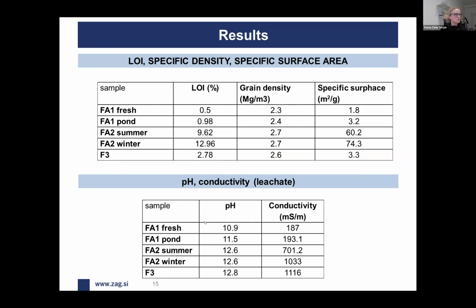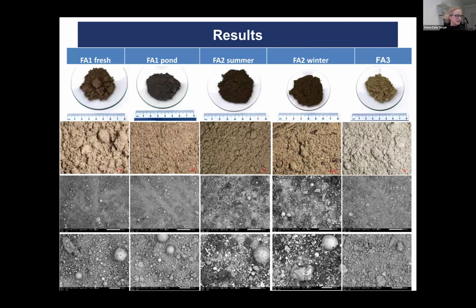Then we specified also some other physical properties, such as loss on ignition, grain density, and specific surface. What is most obvious in the loss on ignition is the fact that in the case of FA2 ashes, the loss on ignition is relatively high in comparison to the other 2 materials. And we know the reason. They're using wood chips, of course. Grain density doesn't really differ between samples, but specific surface also shows the highest values for the FA2 ashes, which we can see also here. It's shown in the microstructural features from the microscopy. They contain different leftovers from the combustion of organic material.